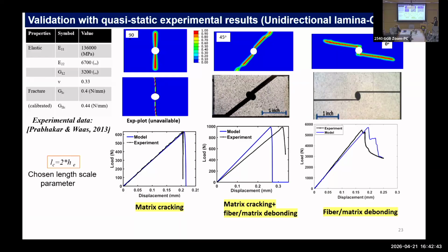So it was very easy. When we went to the orthotropic description of the lamina, it was fairly easy to just straight away use their material constants. I did not have to do any calibration per se, except the two fracture toughnesses. Those of you who are familiar with the phase field literature know that the Ambrosio-Tortorelli type approximation that we are using in the regularization of the fracture term requires the fracture energy to be calibrated if we choose a specific length scale parameter.